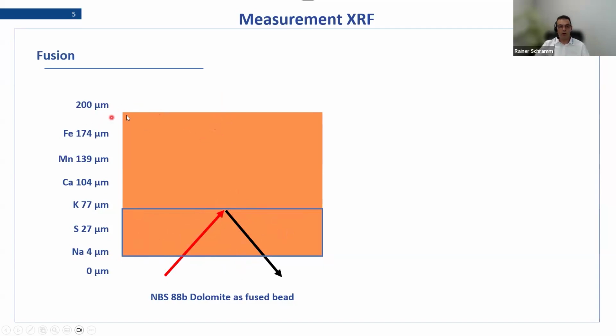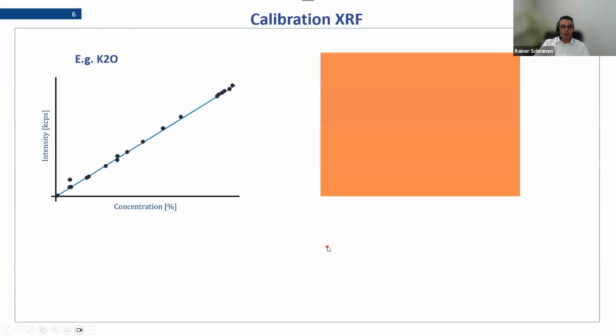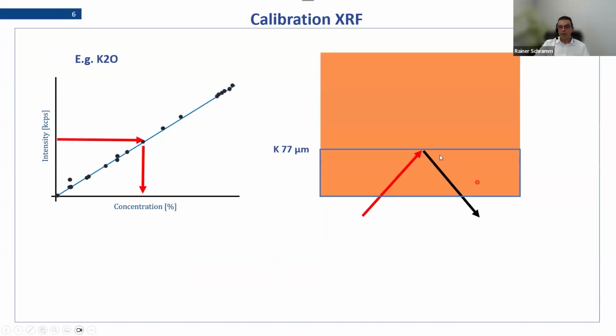And of course, there will be a certain limit, let me say after 2-3 millimeter, when we have X-ray then the complete bead, where then suddenly the thickness will also count. But in the end, we have to think about an analyzed volume, and this means that dilution here is important, but not the absolute mass. So if we just take this potassium example, it means that the intensity you get out of this volume, you will then just correlate with your calibration curve to a concentration, and this concentration then is depending on the dilution factor, which then is calculated out of the sample you weighed and the flux you weighed, but it's the ratio what counts and not the individual weights.